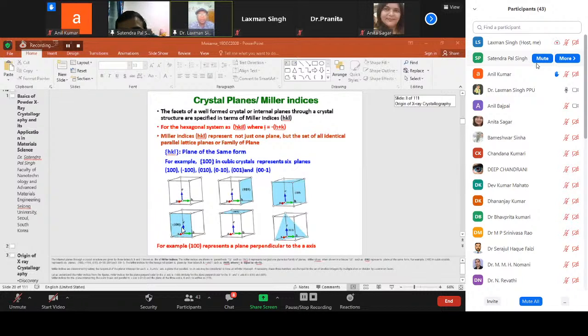So the distance between two 100 planes, with one plane at the origin, for example this one and this one, will be equal to the a-axis. Then the spacing between the 100 planes will be equal to the a-axis in the cubic system. The distance between 001 planes will be equal to the c-axis.